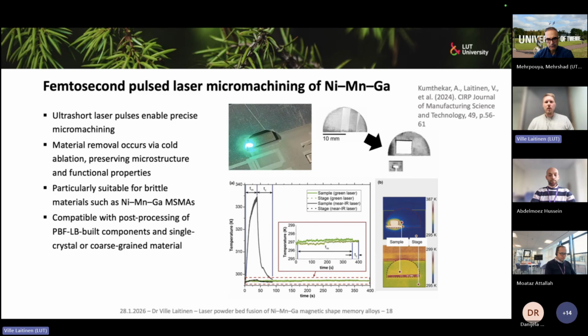Now, what could we do in the future if we have this type of samples? For example, use femtosecond pulsed laser micromachining. So we could make some coarse geometry with laser powder bed fusion, and then post-process it after heat treatment also with a laser like this to cut out these actuating sections. And why we like the femtosecond pulse laser in particular is that we have what is called cold ablation. So we can cut or ablate this material without substantial heat input inside it. So we can avoid damaging the microstructure or the twinning characteristics with this external process.